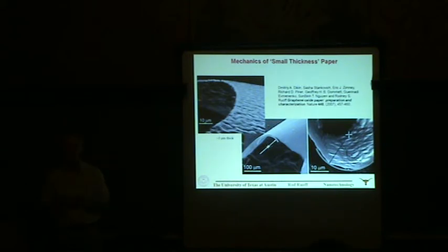So what happened? If I tell you that the density of stacked and overlap reduced graphene oxide paper is about 1.7, what do you think happened? And the modulus jumped up to 800. The density is just about double, to 3.4. The density of diamond is 3.5. The modulus approached that of diamond. So I find this extremely exciting.